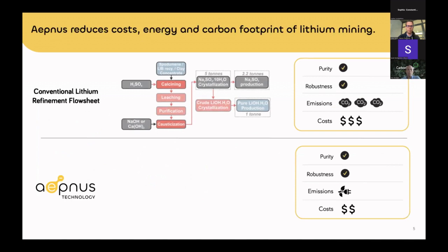To dive a little bit more deeply into how Aepnus technology slots into an existing flow sheet, let me first tell you a little bit about how lithium is currently being refined. At the top here, you see a traditional so-called caustic lithium refinement flow sheet, where lithium is first leached from a lithium containing feedstock, be that a spodumene mineral, a clay mineral, or even an old battery to be recycled, using sulfuric acid. After the sulfuric acid leach, lithium is produced as a lithium sulfate brine, and that then needs to be converted into lithium hydroxide to be inputted into a battery.